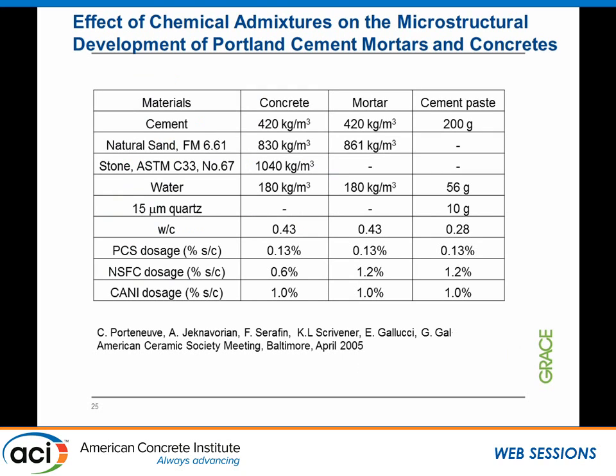So we took a project and looked into this. In this case, it's really just a Portland cement that we made concrete, mortar, and cement paste, and did some strength tests and some SEM tests to really look at what is going on. So in this case, we have the cement and the polycarboxylate, naphthalene sulfonate, and the calcium nitrite. All these were actually published. This paper was published in 2005.